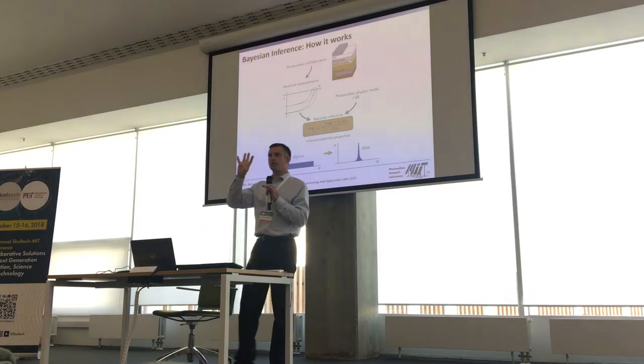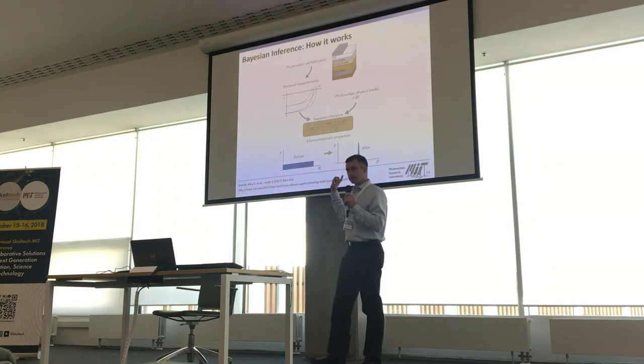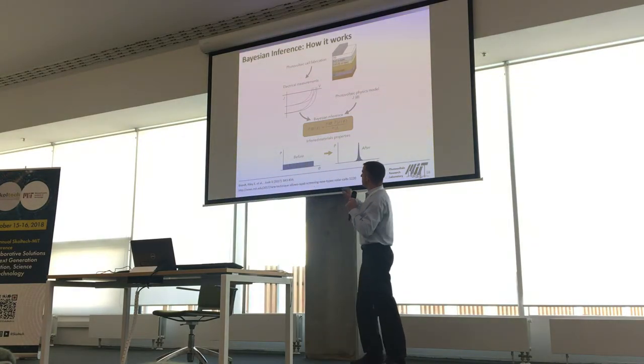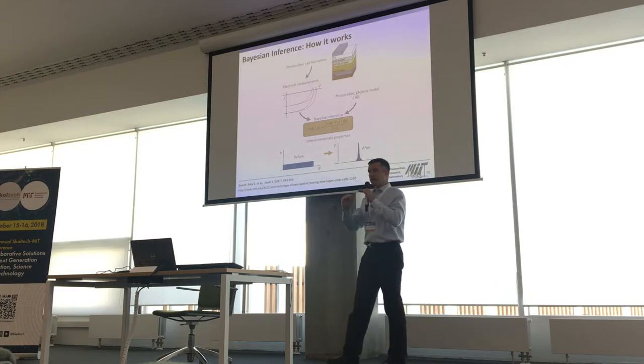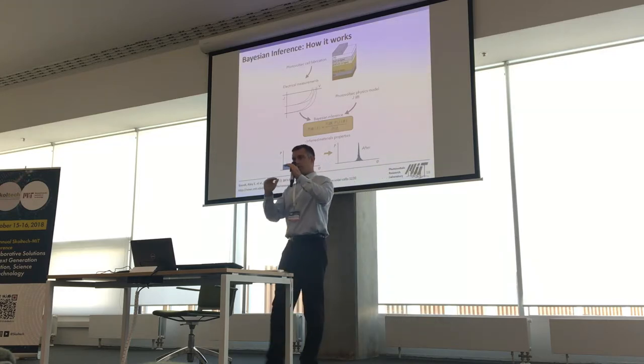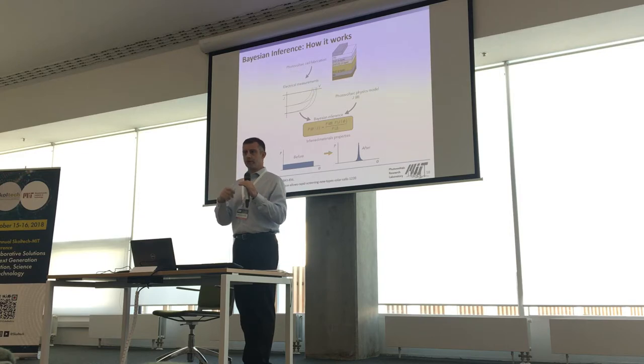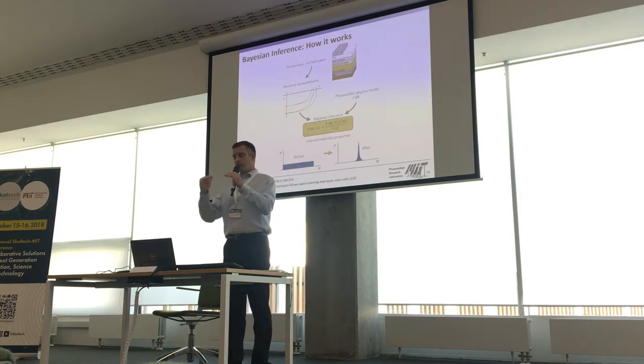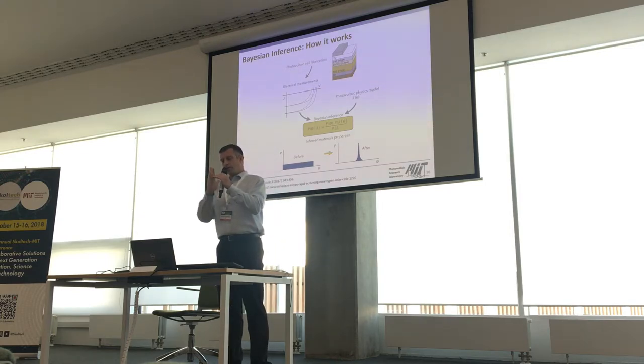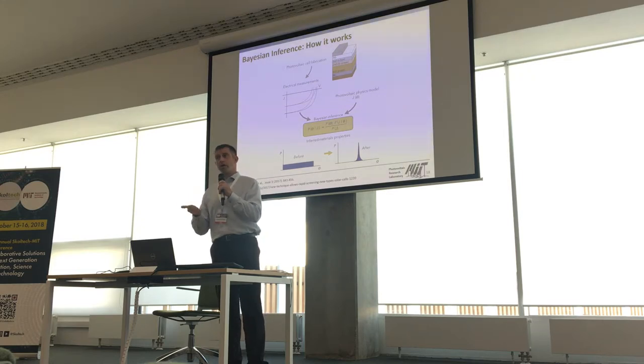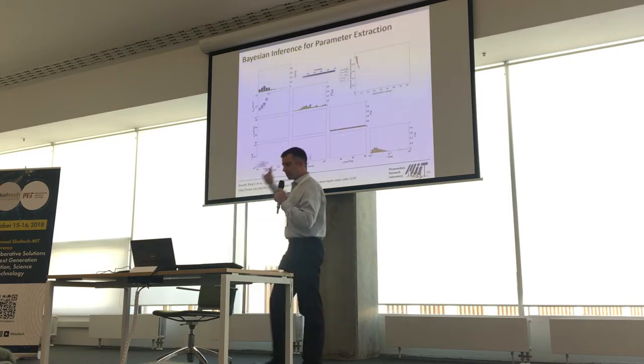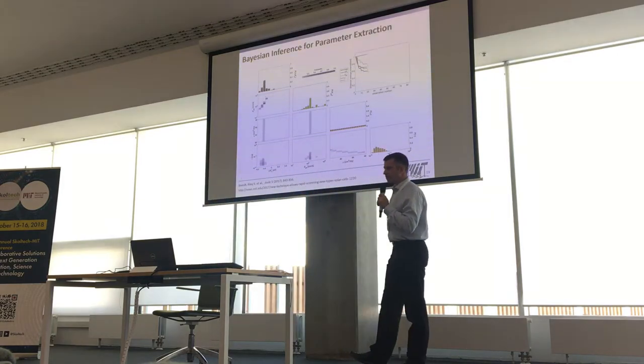So we probed four parameters of interest in an early stage photovoltaic device. We probed the electron selective contact energy difference between the contact and the absorber as a measure of contact quality. We determined the surface recombination velocity at the interface, the bulk minority carrier lifetime, and bulk mobility, two transport properties inside of the solar cell.